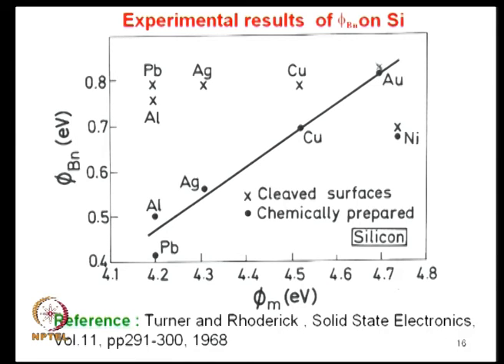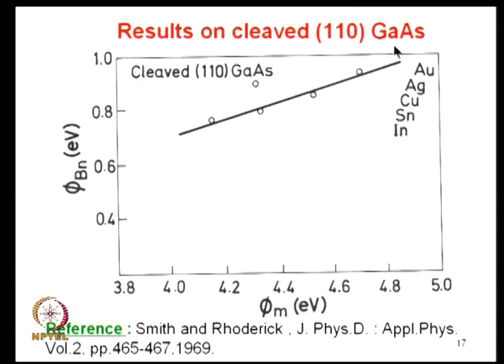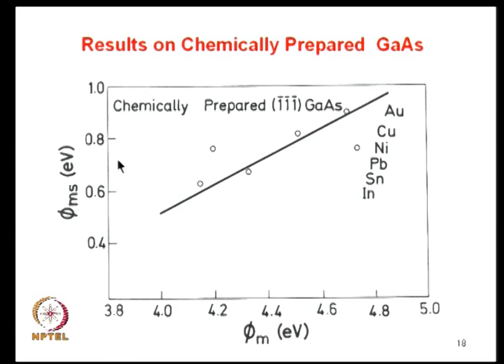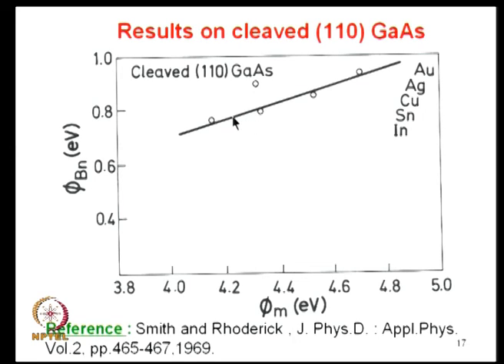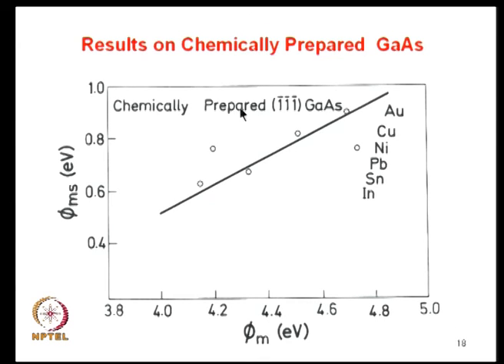Is it characteristic of silicon alone? The same thing they did with gallium arsenide. Gallium arsenide results on cleaved 110 gallium arsenide. Cleaved. There is slight dependence. Phi m varied from about 4 right up to about 4.8. The phi b n changed hardly 0.2 electron volts. So, when phi m changed by close to 1 electron volt, your phi b n changes hardly about 0.2 electron volts. But again, the indication is there of the dependence of phi b n on phi m, but not as much as you expect. This is just freshly cleaved. In the case of silicon, it was flat. Here, slight dependence was there. Maybe the surface state number is less in that 110 plane.